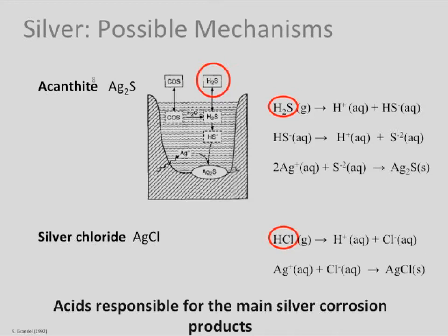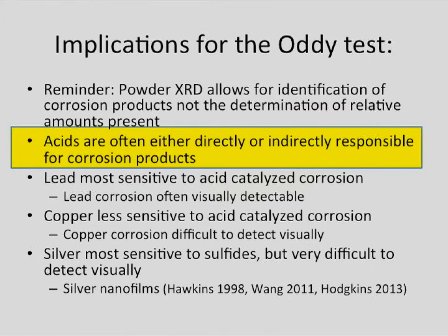In the case of chloride, there are many places you can get chlorine anions, but one of them is hydrogen chloride or gaseous chloride gas, and that forms the chloride anion, which can then form a silver chloride solid on your surface. So in this case, you're more directly forming these corrosion products from acidic precursors.